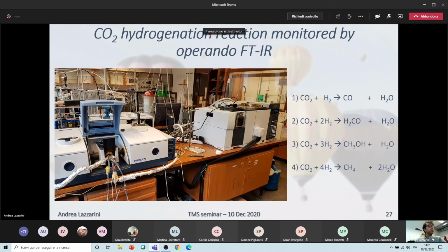So for this kind of systems, I was testing our material in an operando way by performing infrared and X-ray absorption spectroscopy. This is the case of infrared, where we have the material under analysis and we were feeding the reactants, basically CO2 and hydrogen, to the system, and we were monitoring simultaneously the products by means of a GC system and also the infrared evolution of the catalyst. And as you can see, by sending CO2 and hydrogen, we can have plenty of different reactions that can happen to our system. Basically, we were interested in the ones that were producing the highest added value molecules, such as formaldehyde and methanol.